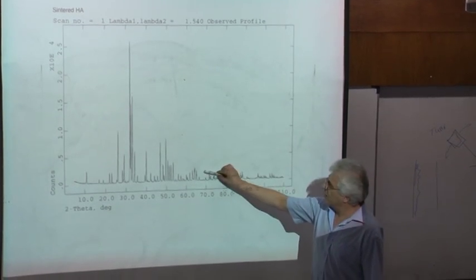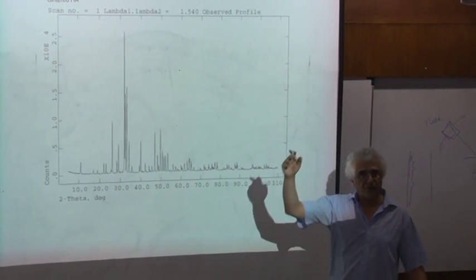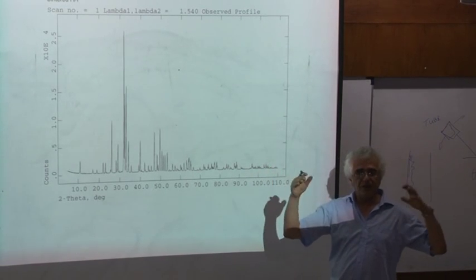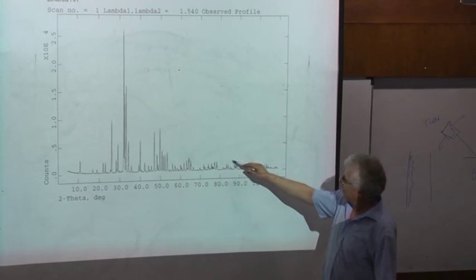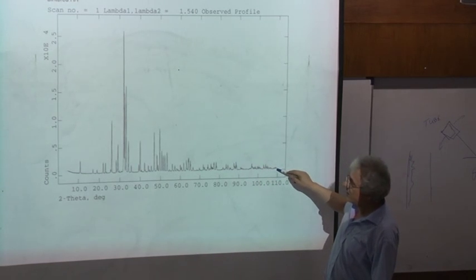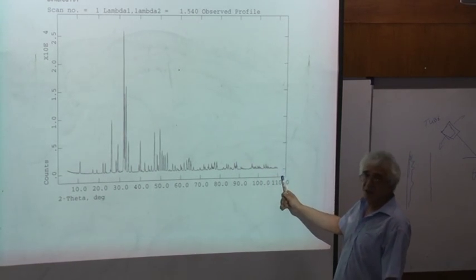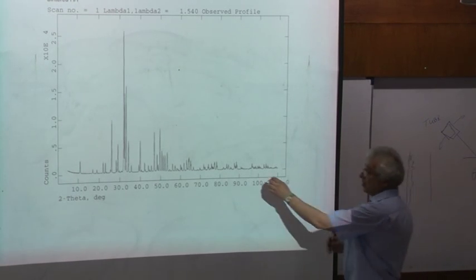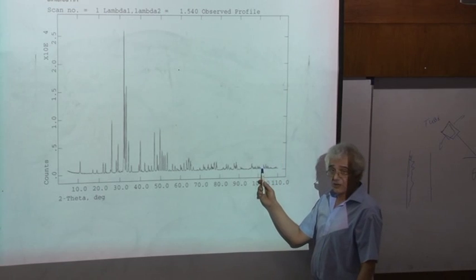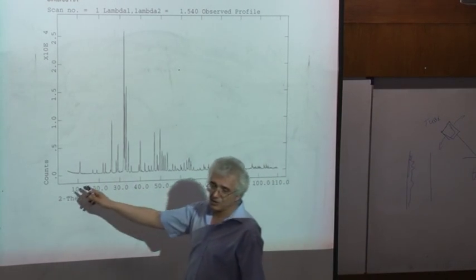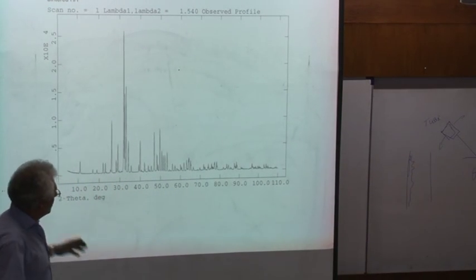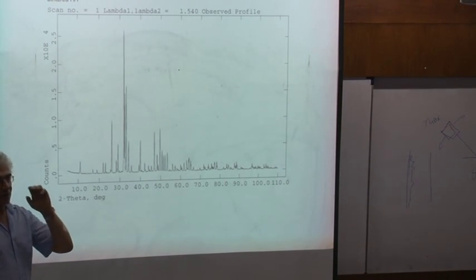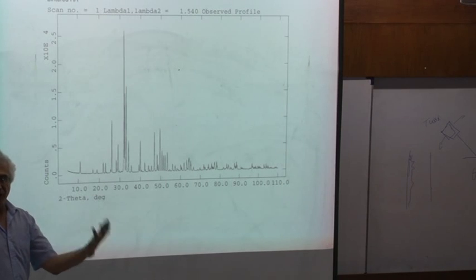And here, weaker peaks, because the scattering falls off, your atoms are vibrating a bit more, they look a bit bigger, you get a destructive interference. And this scattering falls off here as you increase the Bragg angle. The peaks are closer together on this side compared to this side, because remember that each of these corresponds to the reflection from a set of planes.